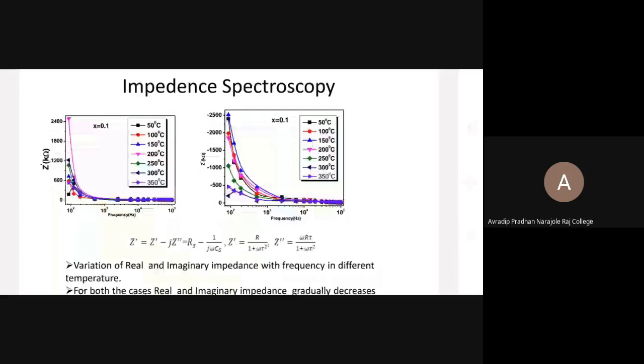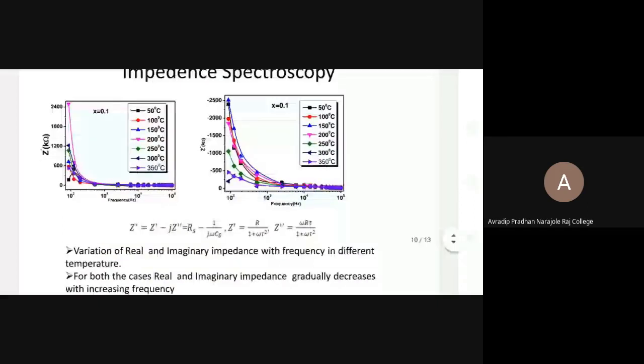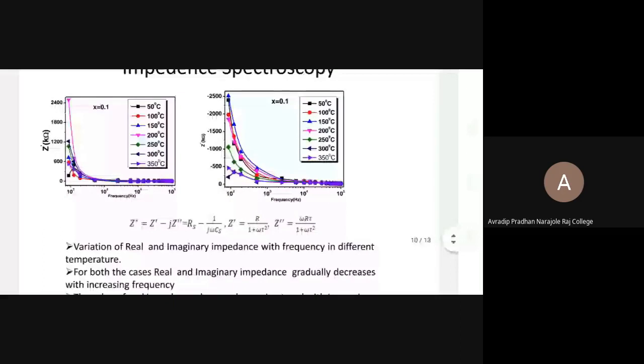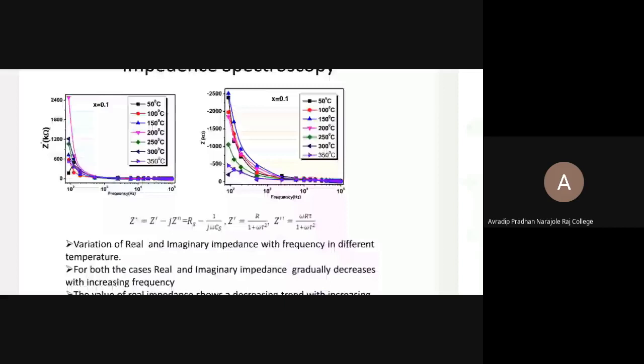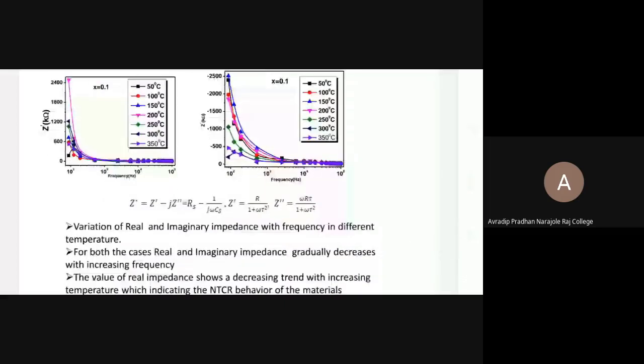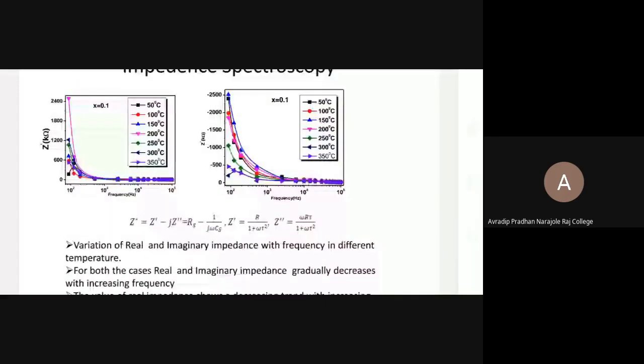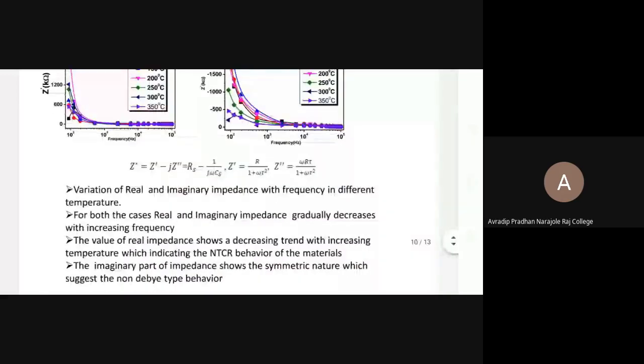In the left hand image, all plots exhibit the temperature dependence of the real part of impedance with frequency. All plots show a low frequency dispersion, and the initial decrease of Z prime value with frequency may be due to the slow dynamic relaxation process in this material, probably due to space charge. Finally, all the curves merge into a single line at higher frequency, which may be attributed to the release of space charge. On the right side, the imaginary part of the impedance with frequency shows a symmetric nature, which suggests non-Debye type behavior of the material.